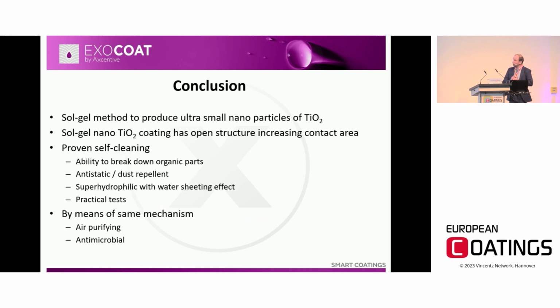So in conclusion, I showed you the sol-gel method to produce ultra-small particles of nanotitanium dioxide. We saw that these particles, or the coating, have a very open structure and therefore increased contact with any organic material. It was proven self-cleaning, giving the ability to break down organic matter. We saw that it was anti-static and dust repellent. We saw this very nice super hydrophilic water sheeting effect with the dirt coming down.